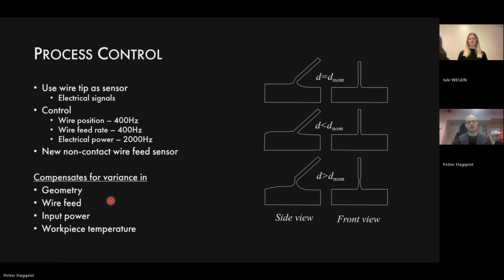And in this project, we found out that we have a window of maybe plus minus 2% in the wire feed rate. If the wire feed rate goes outside of that window, we get a defect. And when we benchmarked the different wire feed systems, we see that even the best ones typically have a natural variation of up to 5%. So without the control system, we wouldn't be able to deposit at this high rate at all.